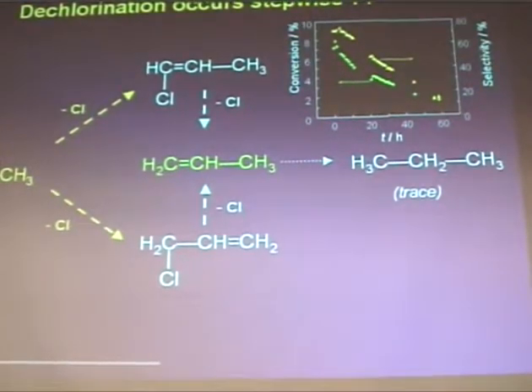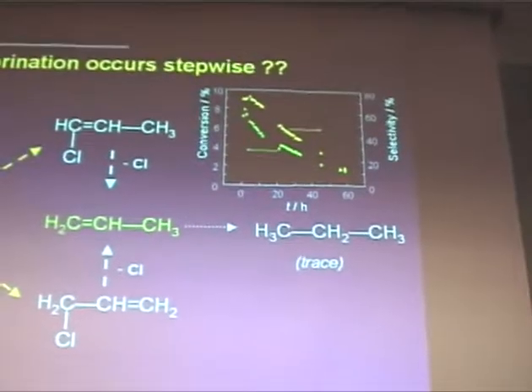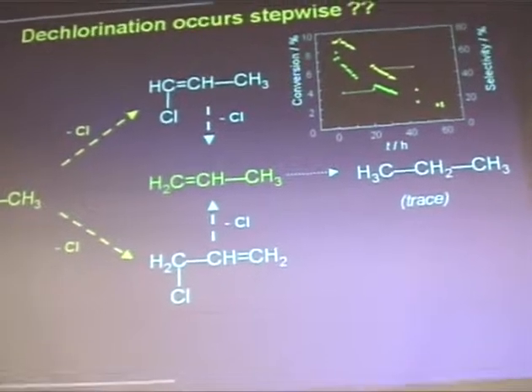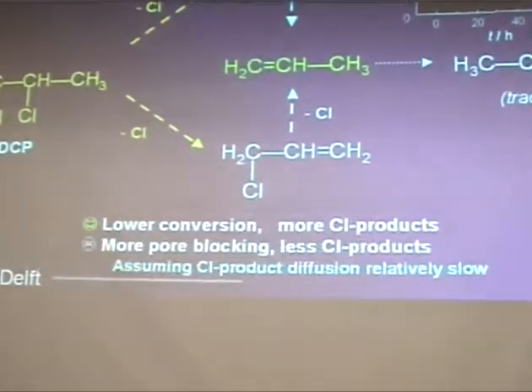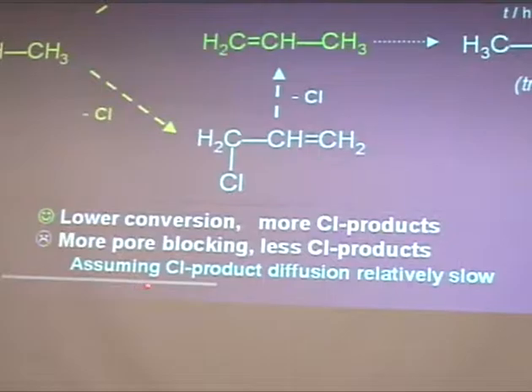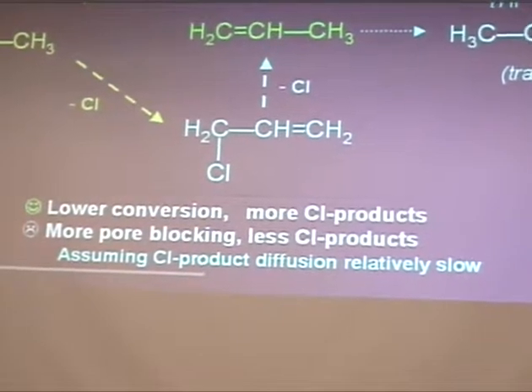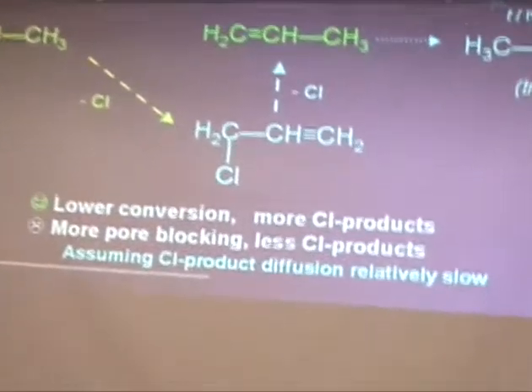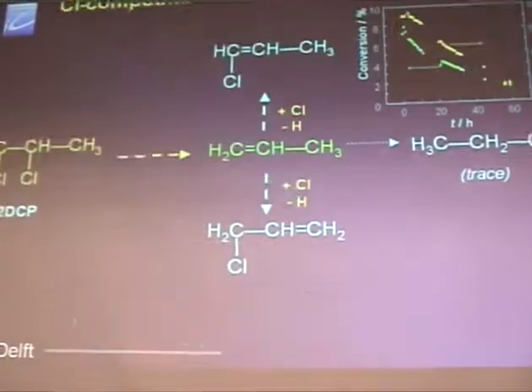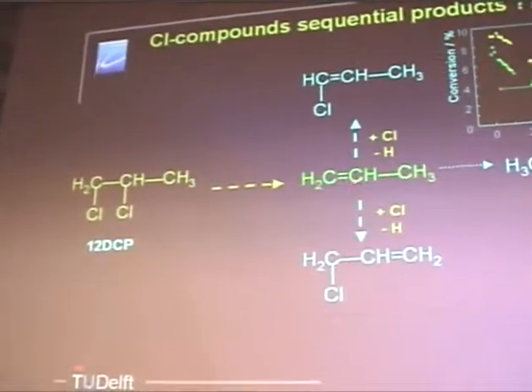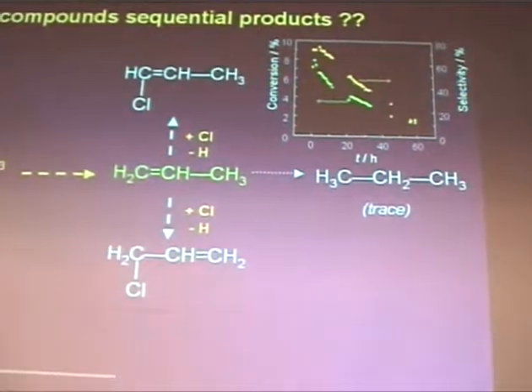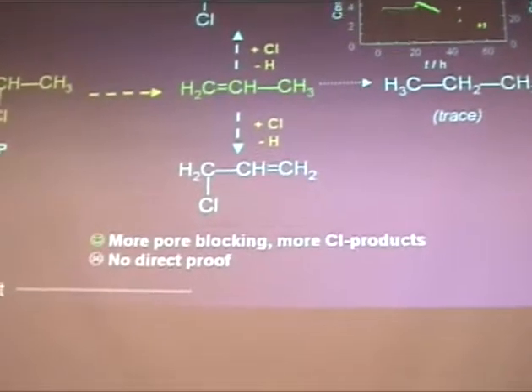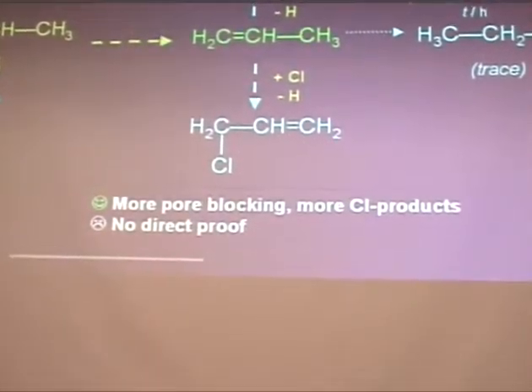Also, we could go to a more kinetic world, that we could say, as people often defend, that you have stepwise dechlorination. First the one chloride, and then the second one. And then you could go in this way, or in this way. Well, at lower conversion you would expect more chloride products, but you would expect that in such a system with mass transfer you would have the end product. So it's not reasonable. The other way around, we also could say we make one step of propene, and then you go in a secondary step to the chloride-containing one. That's possible. Then you say, okay, I have such a mass transfer limitation that I end up with the end product of the A gives B gives C scheme.